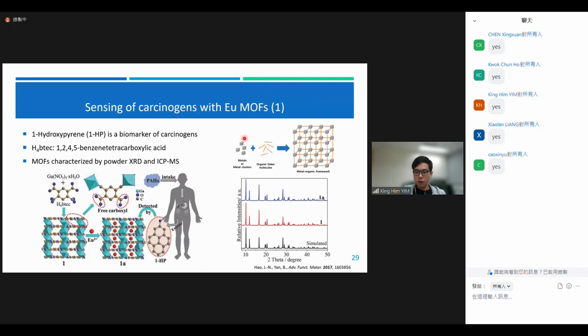But the difference from a cage or helix is that this one is a 3D network. That means the molecular weight is even larger than cage and helix, and the solubility is very poor, and that's why this kind of compound is very difficult to characterize. So scientists use this kind of Eu metal-organic framework for sensing 1-hydroxypyrene, 1-HP, which is a biomarker of carcinogen.